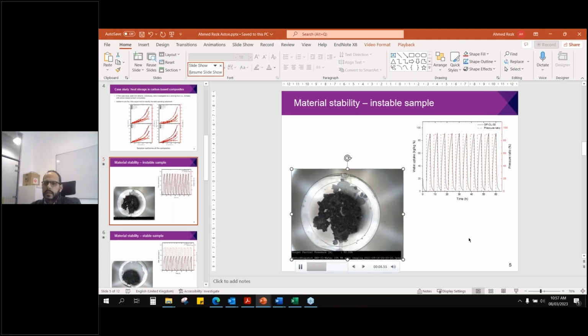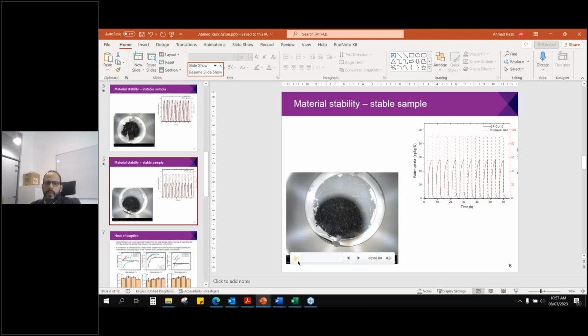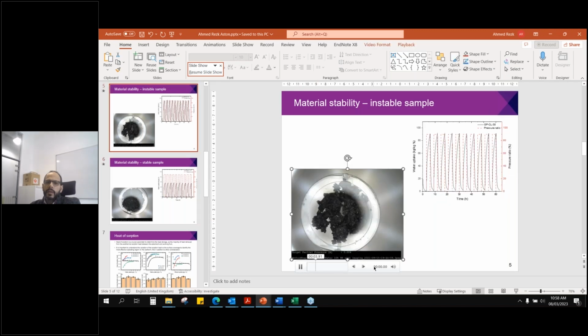Like this material we can see. This material is, no, we move to this one first, sorry. So this one is stable. We can see it can absorb and desorb the water vapor, and the composite physically is still the same without any change in the geometry. Okay. If we look at high concentration of salt in the host matrix, what we can observe is some sort of agglomeration, and it ends up with the salt dissolved and leaving the host matrix.